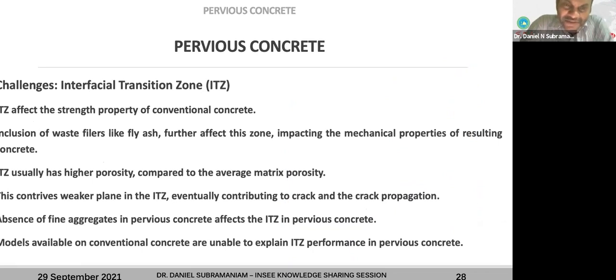Okay, and then the important one, this is something that I actually came across in the recent past, which I found very interesting in some of the research papers. They're talking about the ITZ, interfacial transition zone. So if you take an aggregate coated by cement or the binder, then there is a layer in between the two, which is called the ITZ. And that affects the mechanical properties of the concrete a lot. So most of the time we do microstructural analysis for this. And what I found interesting is that the absence of fines in the pervious concrete is actually an added advantage in the ITZ analysis. But I'm not very sure, because not many researchers are available, and I think we are also trying to do something in the future.